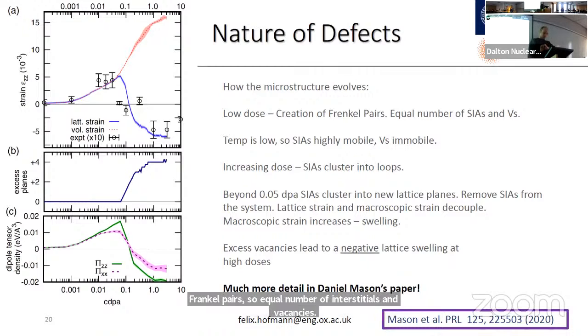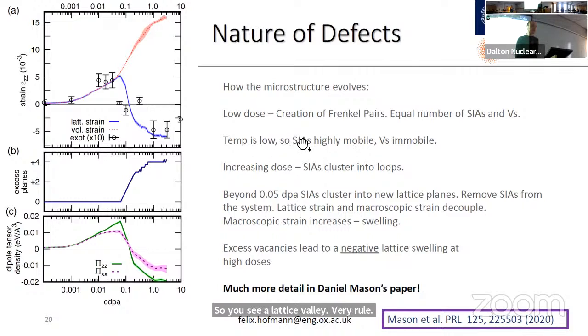So what happens, and how can we explain this peculiar strain? At low dose, you just generate Frenkel pairs, so an equal number of interstitials and vacancies, and you see a lattice swelling overall. Then, because the temperature is low in our simulations and also in our experiments, the interstitials are very mobile, but the vacancies are immobile, right? So the interstitials can move around, and as the dose increases, they start to gather into loops, whilst the vacancies remain distributed throughout the volume.